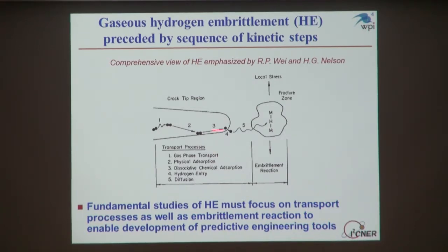And so upstream of this embrittlement reaction, ahead of the crack in the material, there is a series of kinetic steps which is required to get hydrogen into the material. And these can involve steps like the gas phase transport, physisorption, dissociative chemisorption, and then the actual entry and diffusion.